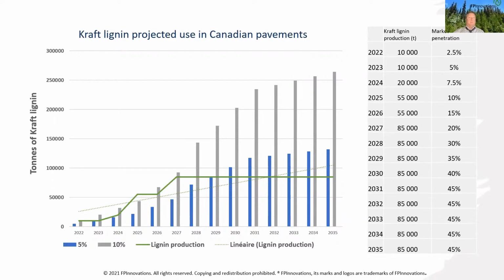A major impediment to these projections is the limited amount of kraft lignin produced by Canadian pulp and paper mills. Currently, only one mill produces 10,000 tons of commercial kraft lignin per year. We projected that one mill would start producing lignin in 2024, another in 2025, and a third in 2028. We know that there's a potential for 1 million tons per year. And there are also other markets for lignin that would create a larger demand, far more than what we're seeing on this graph.